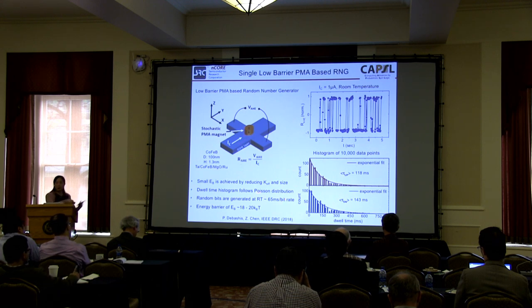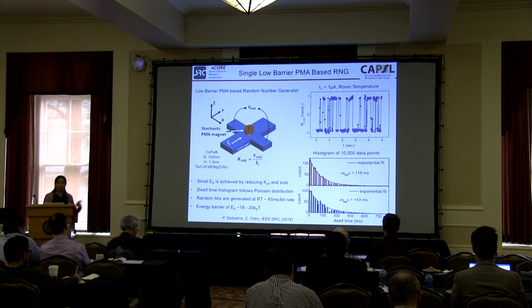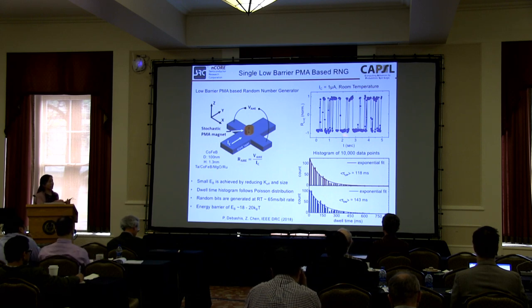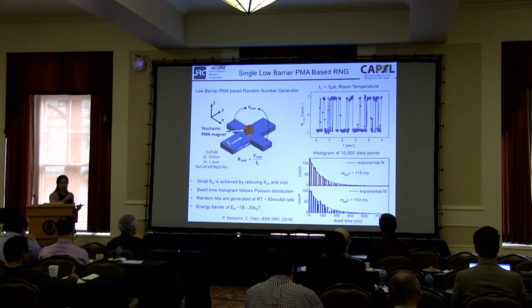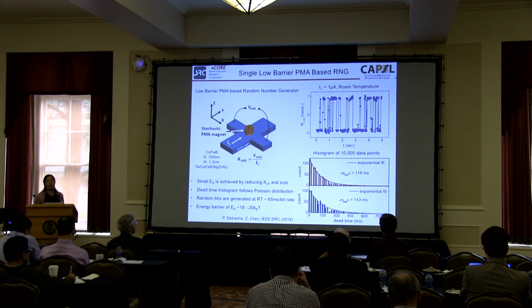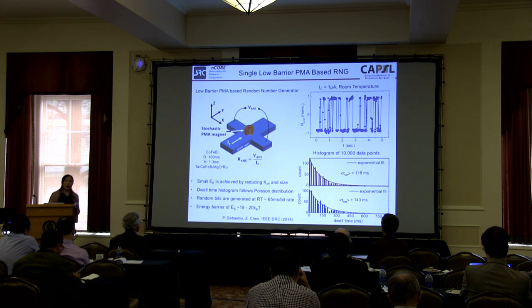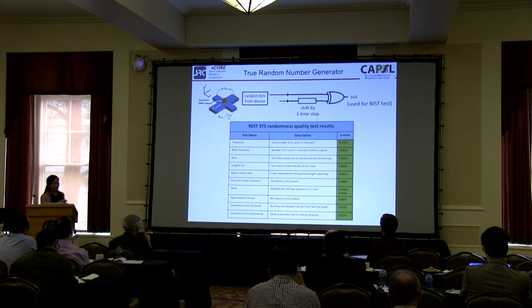It's rather slow. So for the real logic operation, we will try to make the size smaller; here the diameter is still 100 nanometers. Once you have the diameter smaller, it will fluctuate much faster. But here, for our first-time experimental demonstration, it's actually very nice because our logic is not that fast anyway, right? So having milliseconds to read is actually a rather easy measurement scheme here. And you can extract the energy barrier for these PMAs is around 20 kT. Right, so it's not as low as the IMA magnets I have shown, but it is a low barrier compared to what we are used to. And that's why they are fluctuating.